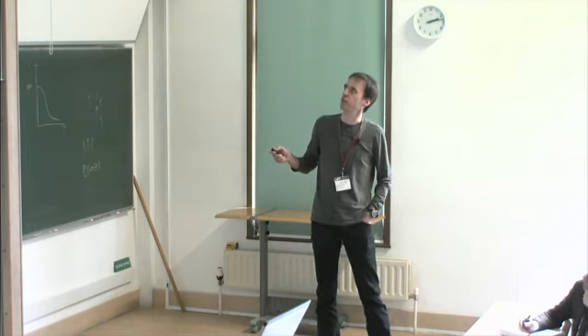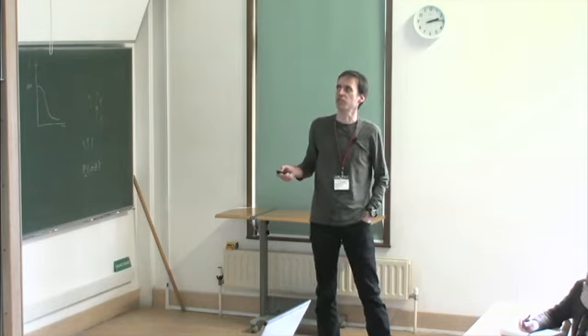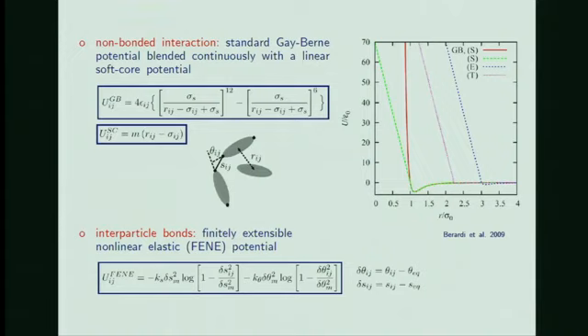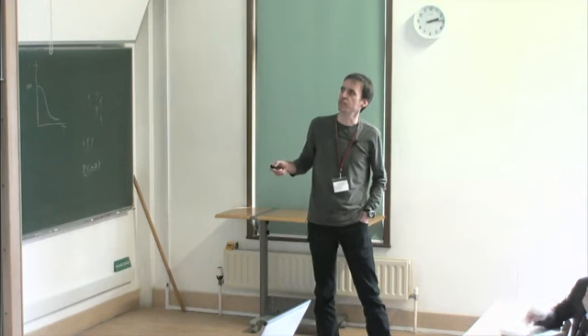and this side-to-side alignment curve would be the red one here. But to get rid somehow of the rather steep power-12 repulsive core, we decided to replace it with this soft-core potential and blend it continuously. And this actually turned out to help a lot in the equilibration of our systems. So this is a typical sketch.